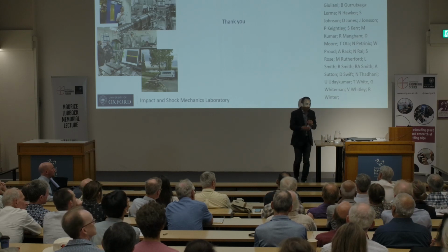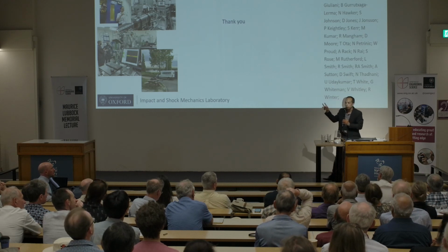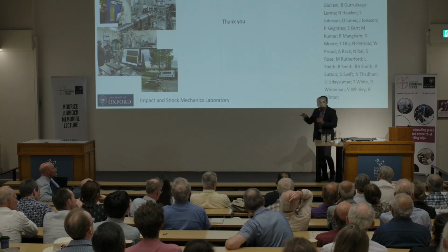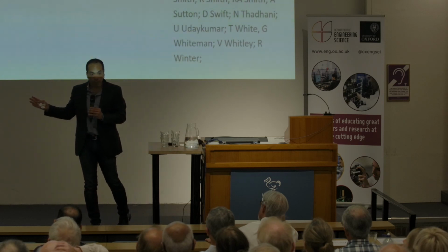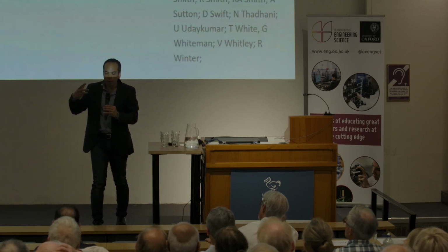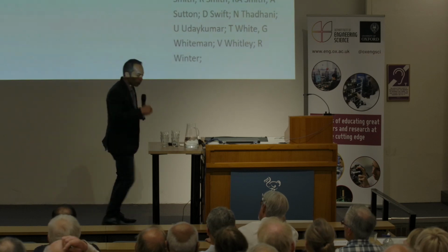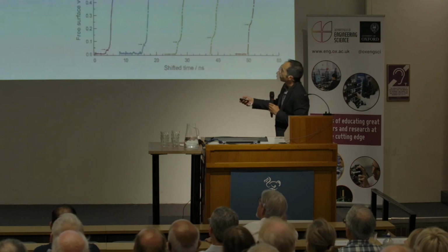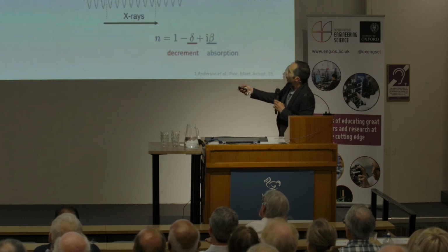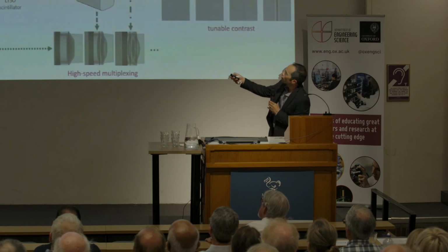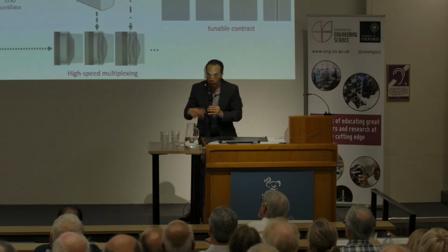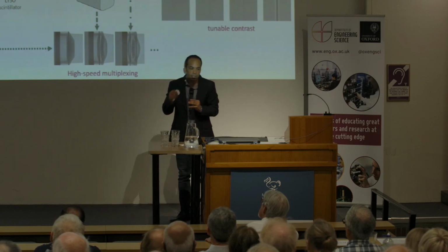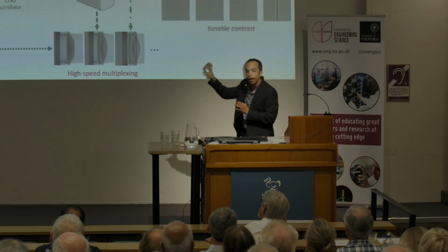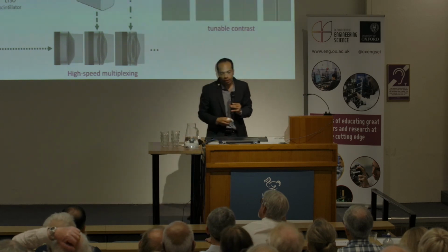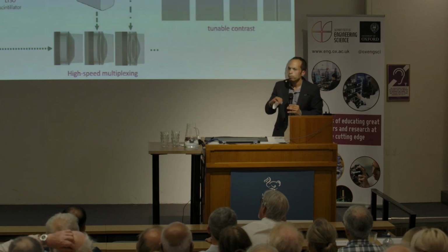I can say yes. I didn't show it because I was more interested in the strength, which I thought would be good for this audience. But when we impact these cavities at above 2.5 kilometers per second, they fluidize. It's an impulsively driven collapse, as you saw in one of the previous slides. Here, there you go, you can see this fluid jet. That can happen naturally, certainly when it's near a surface, and there is of course interest in looking at the interaction of that cavity with a surface, maybe for the reasons you're alluding to, for shock peening or other surface preparation techniques.